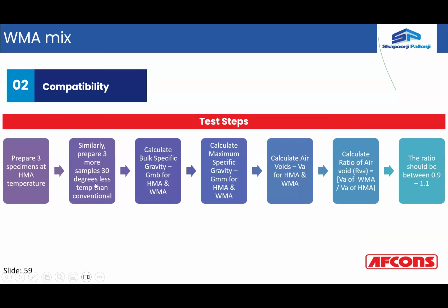Similarly, when you talk of compatibility, you can prepare the specimens using HMA, then prepare 3 more samples using 30 degrees less temperature, calculate the specific gravity, GMB for HMA and WMA, calculate the maximum specific gravities, GMM for HMA and WMA, calculate the air voids, VA for HMA and WMA, calculate the ratio of the air voids, that is VA of WMA divided by VA of HMA. Now this ratio should be in the range of 0.9 to 1.1. That is what basically needs to be checked, and that can be done by varying the doses of the additives.